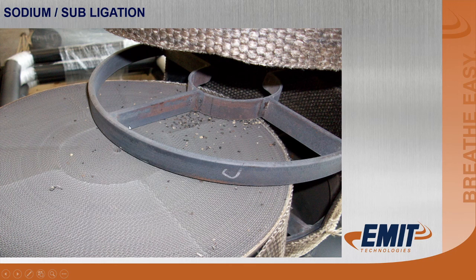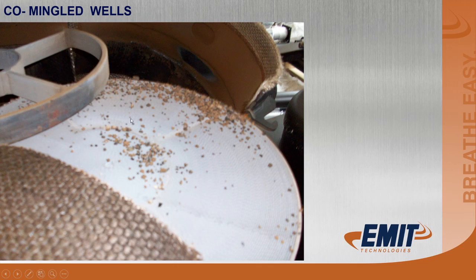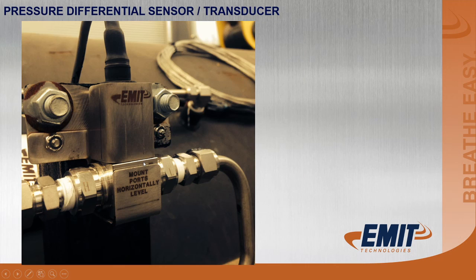And that sodium, as it passes through the engine, reaches a given temperature in the exhaust and turns into a solid. Here's more of the same. Looks like rust or gravel or dirt in there. And this was sodium that caused this.